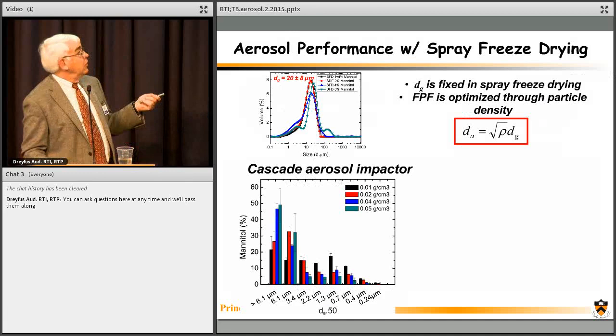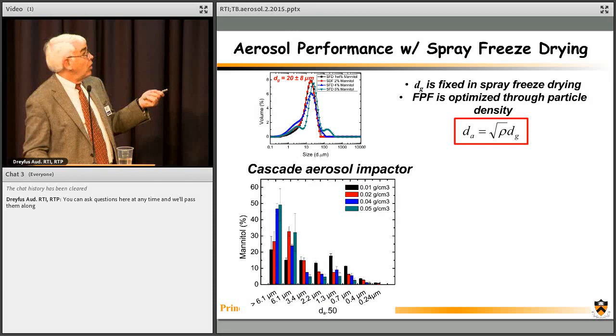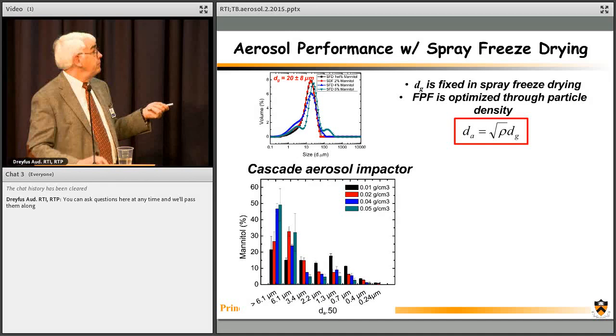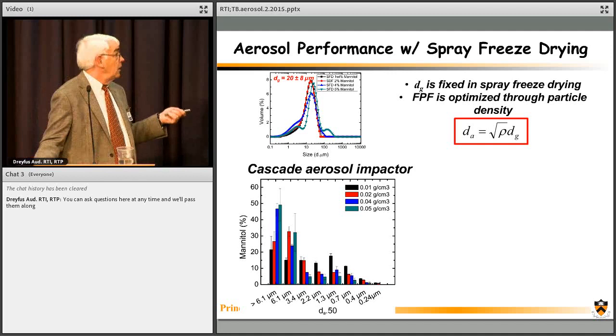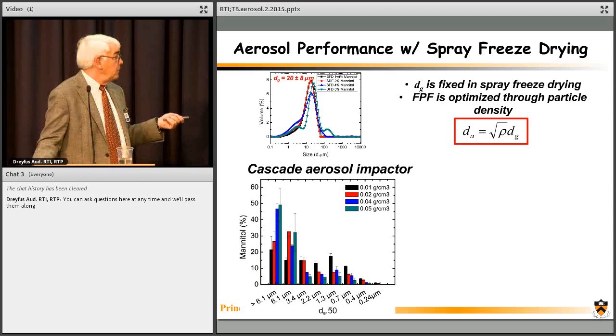Here are the sizes of these particles. You see they're all 20 microns plus or minus 8 for all of these different concentrations. So we can make a particle size separate from its loading. And then this is work in Kim Chan's lab, a cascade aerosol impactor, looking at the mannitol percent, that's how much you're capturing in the cascade impactor at different sizes of particles.